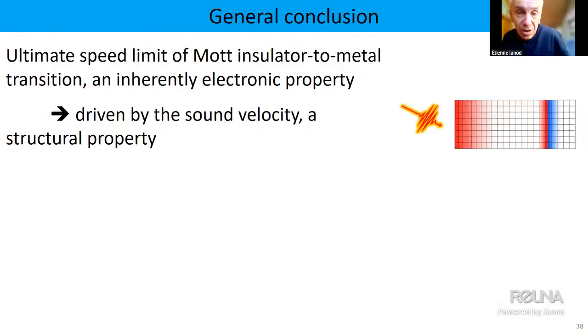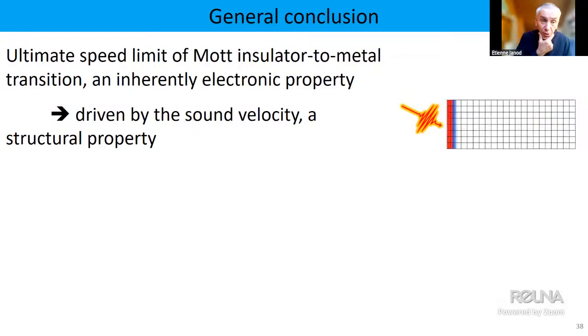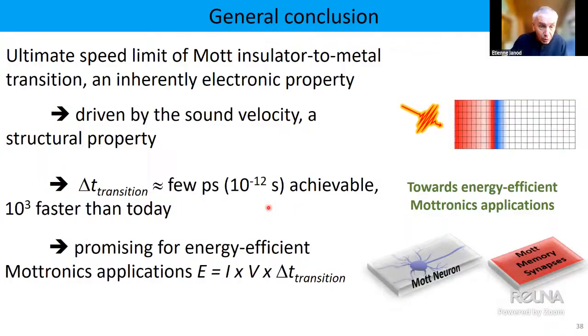So I will now just conclude. What we have shown here proves that the ultimate speed limit for the Mott insulator to metal transition, which is an inherently electronic property, is driven by the sound velocity, which is clearly a structural property, a property of the phonons. Also, what we have shown is that transitions lasting a few picoseconds are achievable if you think in terms of application, and this is at least 3 orders of magnitude faster than what we can reach today if we use only electric stimulus. So it's really promising for the future.